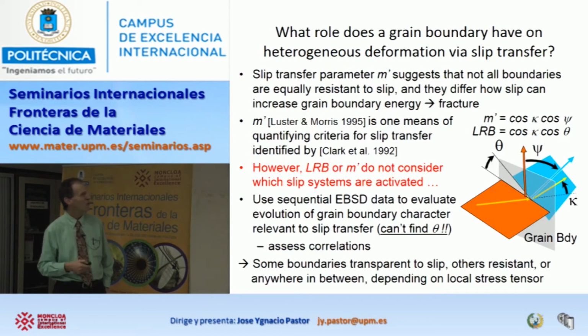So what's the role of the grain boundary on heterogeneous deformation via slip transfer? People have studied this for a long time. It goes back to the 50s, where people first started asking this question. But here's the geometry of slip at a grain boundary that turns out to be pretty useful to think about. If I have slip happening on this slip plane, the orange one, there's a slip vector, and then here's a plane normal. And then if I have a neighboring grain where I have a blue slip plane, with a slip direction and a blue plane normal, then I can just do some standard high school geometry on this.